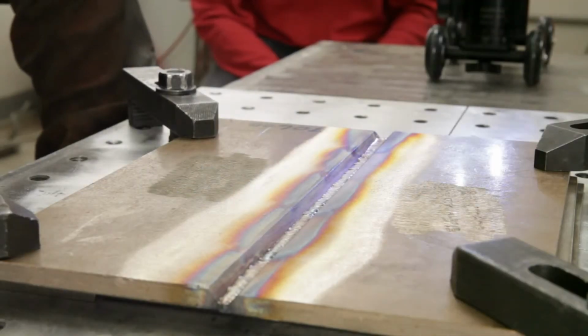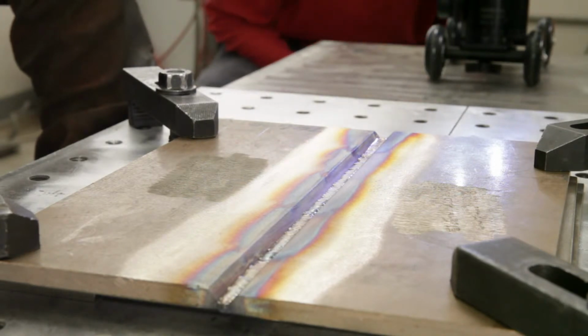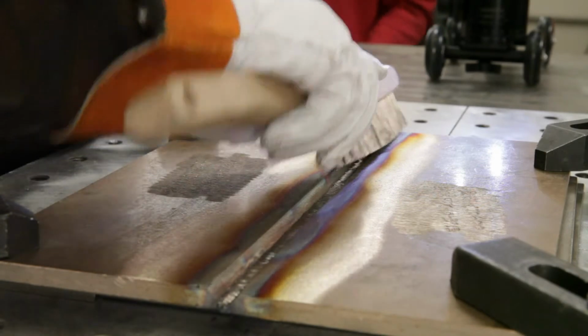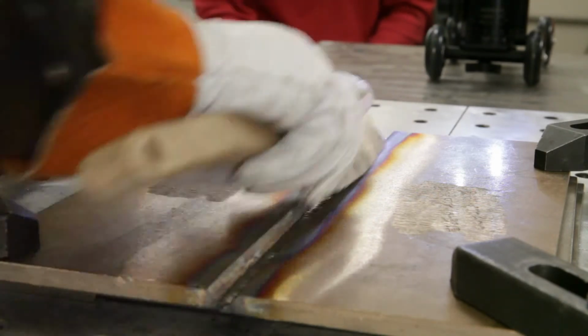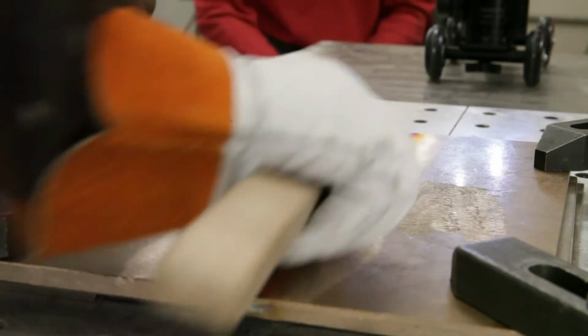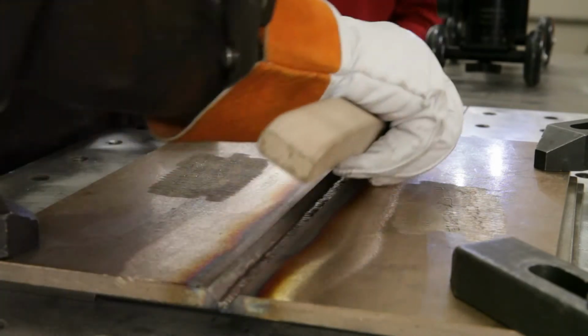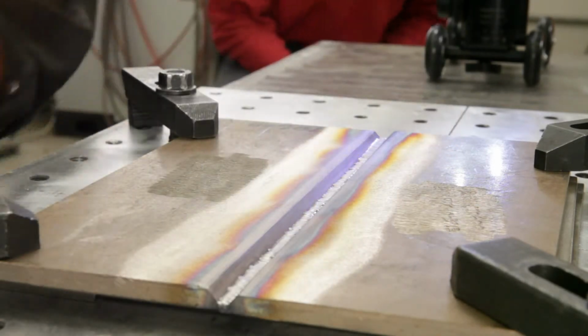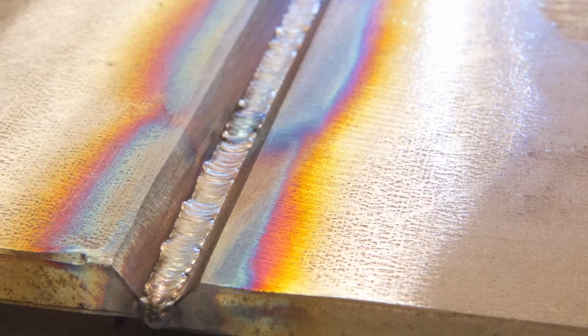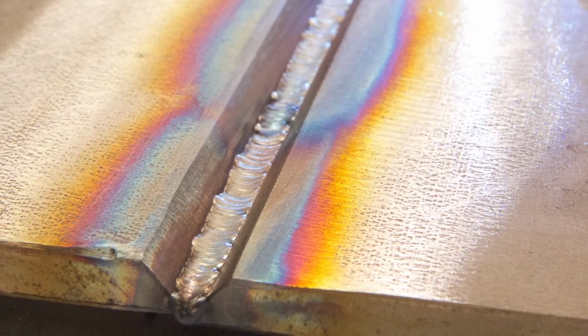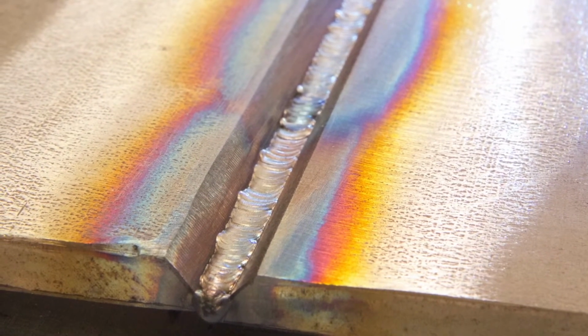Now that the root pass is complete, we'll wire brush it to remove any oxide or smoke on the surface, and we'll inspect to make sure that we have good fusion, no cracks, no porosity or anything else that would interfere with putting in the second pass. And then we'll start our second pass. As you can see, this weld is very even with good fusion to the sidewalls, and we're ready to start welding our second pass.